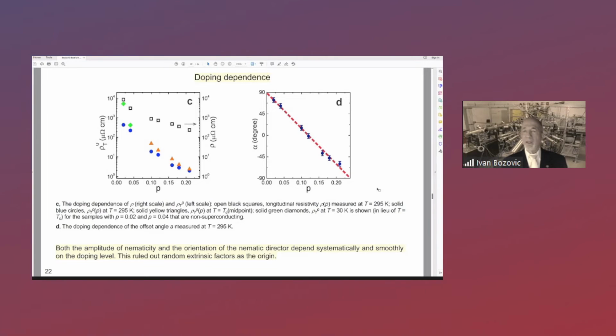Now, in Hall effect measurements, there is usually some offset between the contacts. They are not perfectly aligned, almost never. And that means that you will pick up a little bit of longitudinal resistance, even if you are nominally measuring transverse.